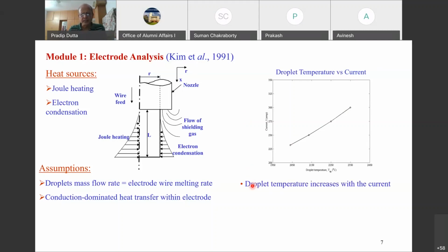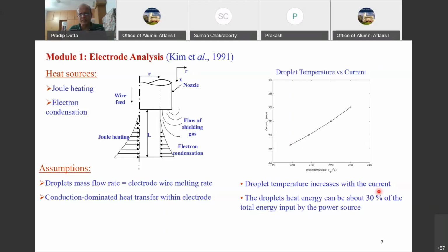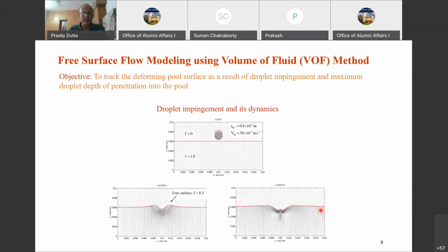And then what we also found was that about 30% of the total arc energy goes into the production of the droplets. And then we now focus our attention on the free surface modeling as the droplets are falling on the pool, how it deforms and how much of these high temperature droplets would influence the temperature distribution inside the weld pool. So that is one way of distributing the heat energy. The other way of distributing the heat energy would be the arc itself. The rest of the heat would go in and be absorbed.